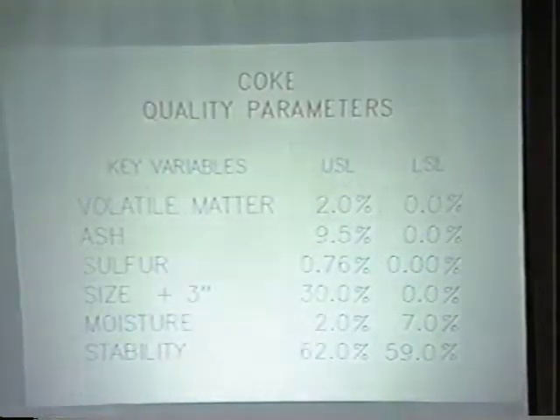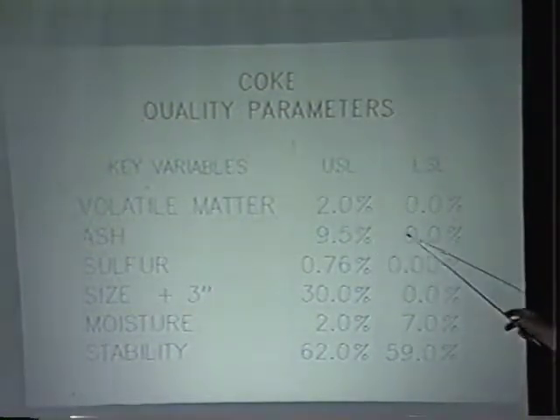Okay, here's some of the parameters we look at in the coke. The volatile matter, we don't want any volatile matter in the coke. We want to coke all that out. We want to get rid of all that. The ash, now this is controlled by the coal. The sulfur is controlled by the coal. We use low sulfur coals, and we use low sulfur or low ash coals. We pay a little more premium for it, but it gives us what we want.